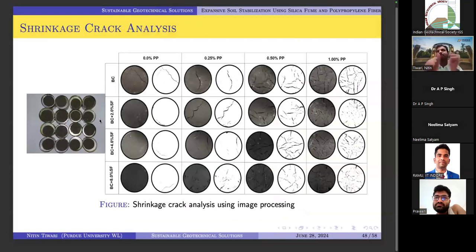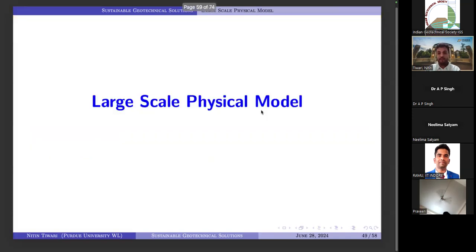This is very interesting. Since I talked about the clay particles, clay soils, we did this shrinkage analysis also. This is your mercury displacement pad which we use in the lab. We did a very nice analysis using image processing, and we figured out how the cracks or shrinkage are taking place inside the samples. We did the complete image processing analysis. It was really nice, and we can employ that kind of analysis in larger areas, taking pictures from drones and doing these kinds of tests for large sites also.